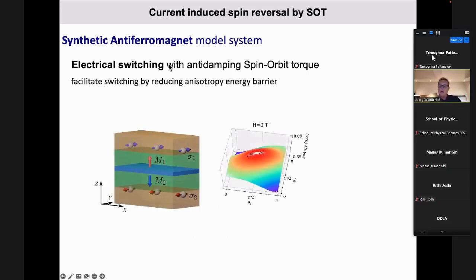And here we apply again a little trick. We normally have the energy barrier, which corresponds to the anisotropy energy barrier, which is quite high. One of those states has to overcome this energy barrier to flip into the other minimum. And this energy barrier is extremely high, so high that thermal fluctuations are far from enough to do this at room temperature. So normally those systems are absolutely stable and they will stay in one of those states.